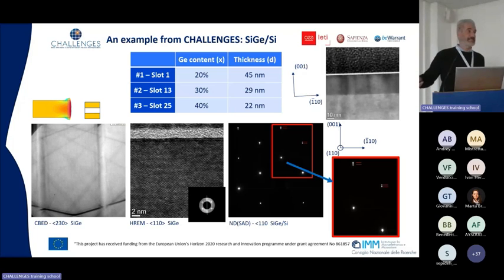Geometric phase analysis in high resolution, and nanobeam diffraction, or even selected area diffraction, just trying to keep our beam as small as possible in our conventional and 20 years old microscope. You see that it's clearly possible to see here two spots. So you can perform the analysis we did before and extract the strain.